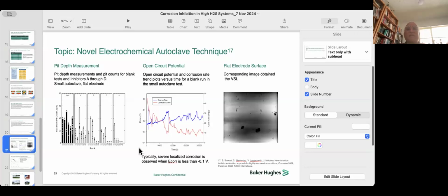So we have software that, when we see a big bump in our corrosion potential, then we do LPR and we see what the corrosion rate would be. And then you can count these. We have had a patent and other things on this. We can count where they are. And there was very nice work done by colleagues of mine, in which we can associate each one of these pits with the actual images. So we really had a nice advanced electrochemical technique for determining this.